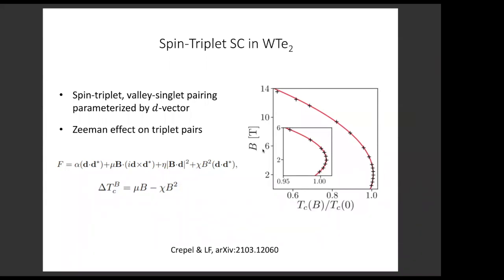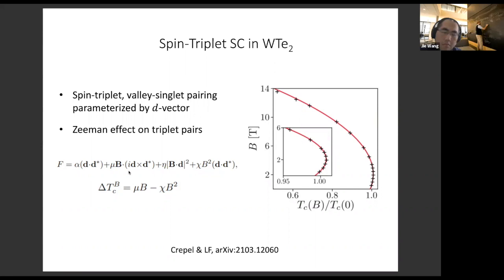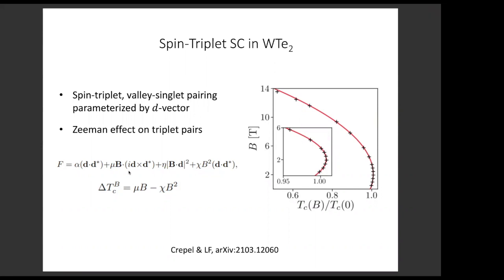So once we include that term, we can obtain a very simple result for how TC depends on magnetic field. There should be a linear term and then a quadratic term. The quadratic term just comes from the ordinary pair-breaking orbital effect, while the linear term comes from this Zeeman term. And then we can fit the experimental data with theory. You can see a very nice agreement. So again, this makes us believe that the superconducting state in tungsten ditelluride is actually a spin triplet. Next slide.